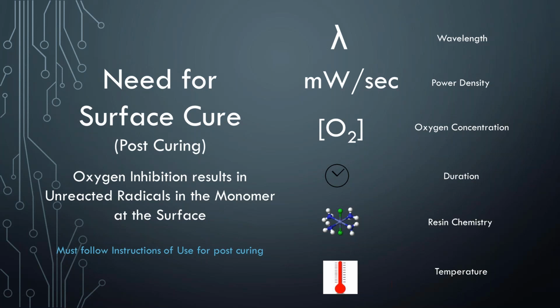So we'll see curing units that apply multiples of these rules on the right hand side. For example, the Form Cure from Formlabs has heat and a high spectrum light to complete the surface cure, which is what is needed for their surgical guide resin. For example, our Variguide resin currently needs a low oxygen concentration and a high power of light and high power wavelength to be able to complete the surface cure.